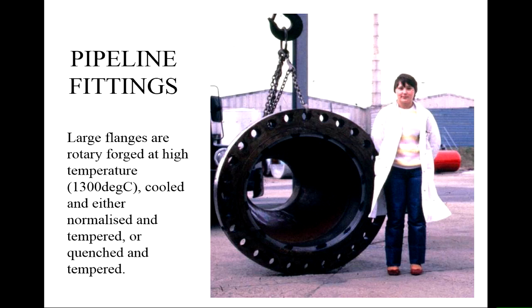So this is a rotary forged, high temperature, large flange section, which is to go on a large distribution pipe. So it was forged at 1300 degrees C. It was cooled. For this particular one, it's either normalised and tempered or quenched and tempered, depending on the cooling rate for that particular flange system. And I just wanted to show the size of this, really, for the picture. It's not something that you can easily handle.